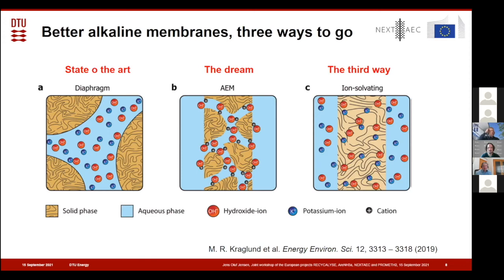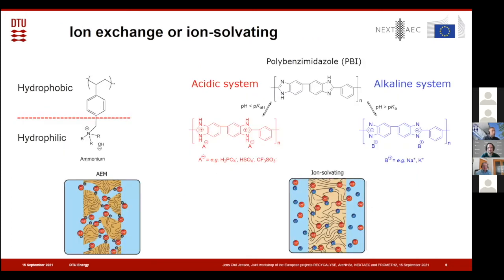The third way that we are pursuing in the projects mainly is the ion solvating membrane. Here we don't have any pores, we just have a membrane material that can dissolve the electrolyte and all the ions and water and everything. So you have a sort of blend of membrane and electrolyte with a very high conductivity. You can see the traditional idea to the left with the AEM, where we have these side chains, and that's actually the weak part of the polymers typically. That is where it's degraded first, these side chains. And if it loses them, it loses the conductivity. So that's the beginning of the end. We don't have these side chains.